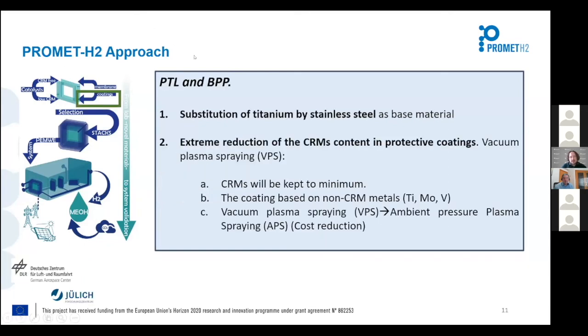Regarding the PTLs, the porous transport layers, and the bipolar plates, I think this is one of the keys of our project because, as you know, this represents almost 60% of the cost of the stack. Then if we can reduce the cost here, we can reduce the cost overall of the stack. We wanted to replace the titanium, that is the base material for this kind of component, with stainless steel. And then we will have an extreme reduction of the critical raw material using protective coating.